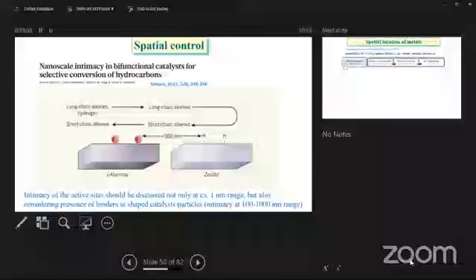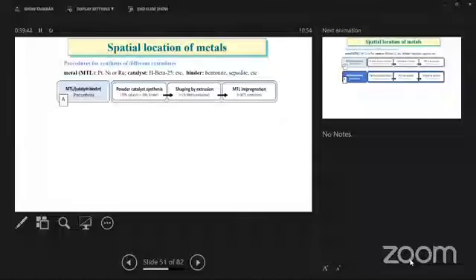Brian, who is a good friend, didn't make extrudates himself. They purchased commercial extrudates from Shell. And then they really had a challenge to introduce the metal either on the binder or on the acid side. So they had once again the ready-made extrudates, and they tried in a very special way to put the metal either here or there, either on the binder or the zeolite. We made it slightly different because we have this possibility of making extrudates ourselves.